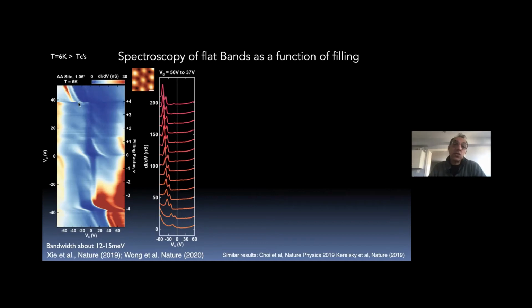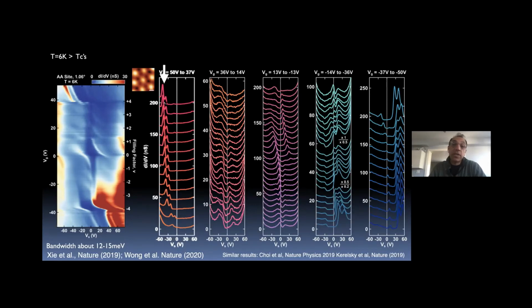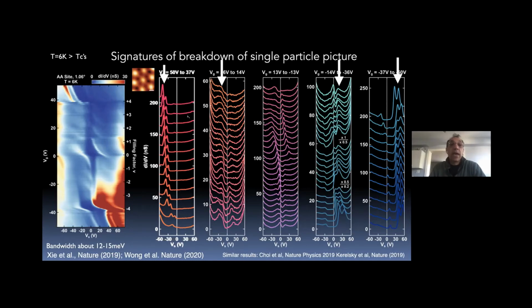These two lines are the two sharp peaks of the two flat bands, and you can see all this blurriness happening in between, when they are fully occupied, below the chemical potential, or fully unoccupied, above the chemical potential. This is the first surprising thing we observed: why is it that these two sharp features become extremely broad as you partially occupy the bands? Not only the state that you're filling near the chemical potential, but even the state that's very far below the chemical potential also gets very broad. The basic message is that this is caused by strong charge fluctuations due to the strong Coulomb interaction in the system. It's a very hard problem to model theoretically, as I'll show you in a minute.